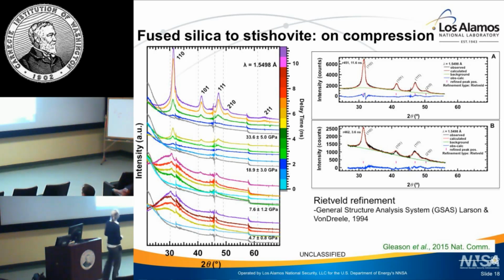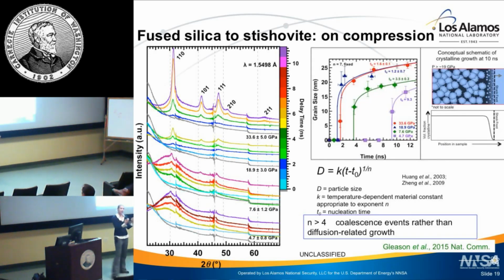The next way in which we looked at our data is to assess the grain size. Now, we know the standard Scherrer equation essentially relates peak width with the grain size. Here I used a modified approach that also includes some component accounting for the strain in our sample. Okay, so it's called a modified Warren-Averbach approach. But I'm able to essentially look at my diffraction peaks, pull out the peak width, and assess grain size.